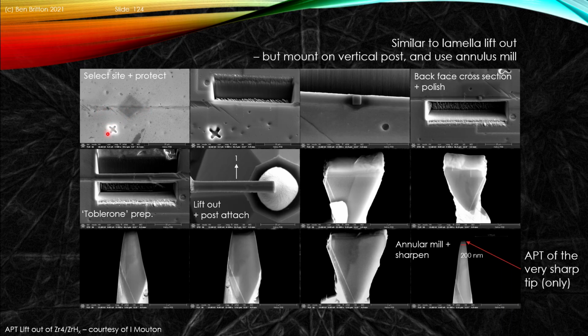So we did site-specific work by producing fiducial markers, put a protective layer. We then prepared a Toblerone type region with controlled understanding of the area that we want to look at with markers. We then produced effectively the Toblerone, we lifted out this Toblerone, put it on the end of a manipulator, brought this towards a post, we then effectively take this Toblerone on top of the post, we then cut off a section to enable us to have a freestanding object, and then we do a series of annulus mills where we kind of use a donut-like polish to sharpen this down to a very sharp point with a typical radius that's less than 200 nanometers.